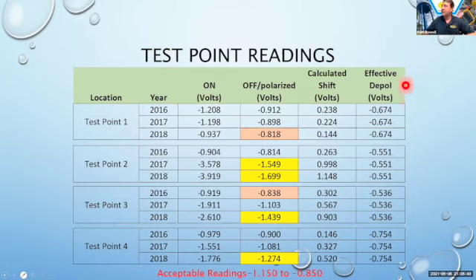For this effective depolarized potential, what they're using is that sometime back in history, they allowed their system to depolarize, maybe get down to some native state, and they recorded those potentials. So they're utilizing that as their depolarized potential. And for those areas where, like in this case, there was a potential less negative than the 0.85, they're able to compare that to this depolarized potential, and this calculated shift is the difference between those two values: 144 millivolts, or 0.144 volts. So that's more than 100 millivolts, and they're effectively showing that they are cathodically protected at that point.